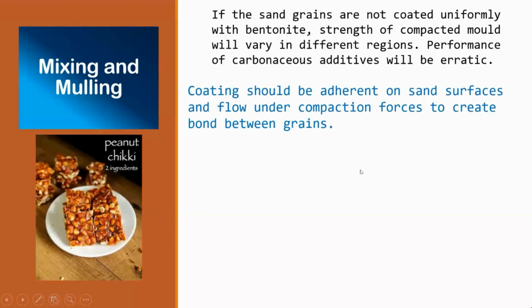Coating should be adherent on the surfaces and flow under compaction forces to create bond between the grains. Adherent on the surfaces is why you require a mulling action. You require energy to push the bentonite onto the sand grains and make it stick to it. Then when you are compacting, this bentonite which is resident on each grain will stick to each other under the compaction forces and produce the mold.